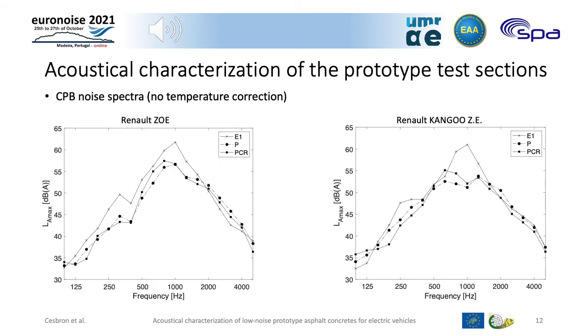On this slide you can see the CPB noise spectra for both vehicles, Renault Zoe and Renault Kangoo ZE. For both tested vehicles, noise spectra have a similar shape on the reference test section E1 with a clear peak at 1000 Hz. On prototype test sections, this peak is attenuated by 5 dB for the Renault Zoe and the maximum is shifted to 800 Hz on the PCR test section. For the Renault Kangoo ZE, the peak at 1 kHz is reduced by 10 dBA and the maximum is shifted to 630 Hz for both P and PCR test sections.